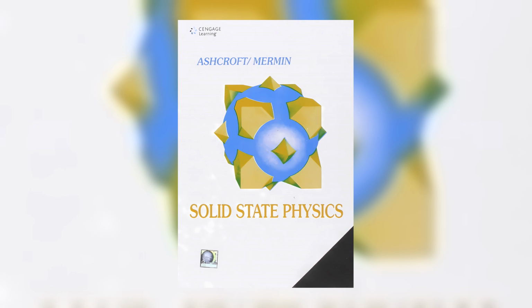Spin enters only through the Pauli principle, which chains spin symmetry to spatial symmetry, and spatial symmetry carries a Coulomb price. So the energy depends on relative spin direction, even though no spin term appears in the Hamiltonian. The hydrogen molecule singlet-to-triplet splitting is the whole mechanism in miniature, and it demands abandoning independent electrons. Exchange lives in the correlations that band theory throws away.